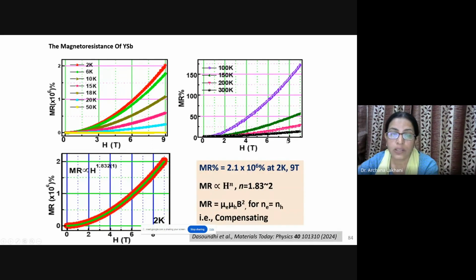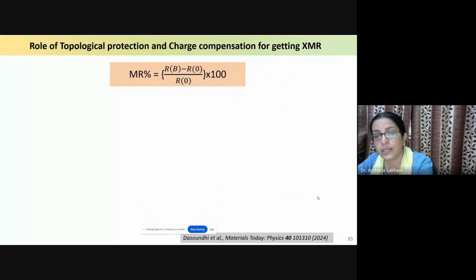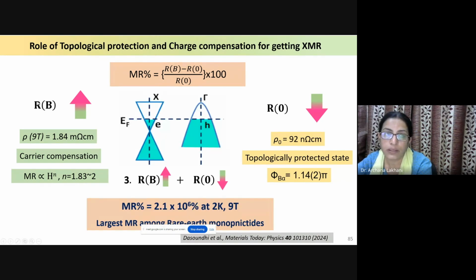So if you see, it has such a large magnetoresistance at 2 Kelvin and 9 Tesla, and the origin is that it has a large compensation. That means the numbers of electrons and holes present in this system are almost equal, and the mobility of these charge carriers is very, very high. These are a few reasons which cause such a high magnetoresistance, XMR, in this material. Very fundamentally speaking, this is the definition of magnetoresistance. To have this large change, we should have a large resistance with the application of field and low resistance in the absence of magnetic field. So if we have a cleaner system, this ratio will enhance, and that is what is happening in our system.